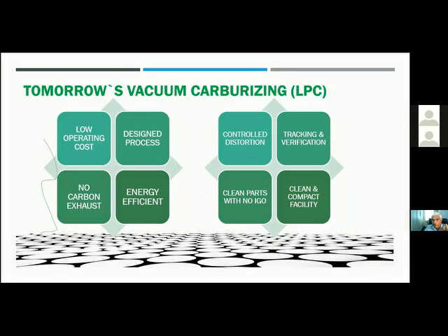They're constantly generating 4 to 5 kilowatt per square meter compared to 14 kilowatt per square meter. Huge energy saving. I'm not saying there is no distortion, but it's a controlled and repeatable distortion, which can be handled by soft machining. Completely built-in tracking and verification process. You have components which are extremely clean, other than when you use oil quenching, when you need to clean the oil, with absolutely no IGO. In fact, in the continuous system, you can take the components and send them for assembly. You don't need any post-treatment cleaning or washing.